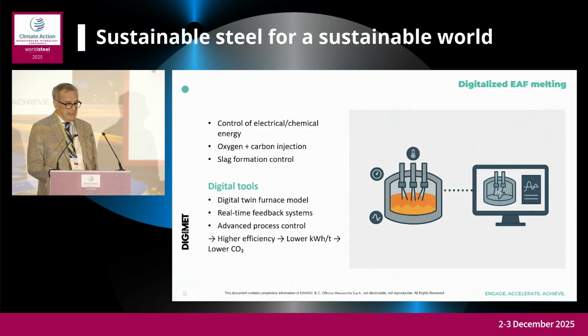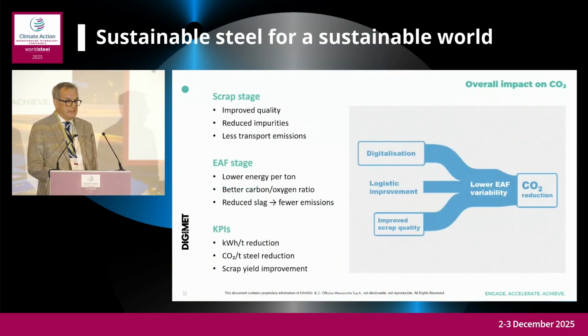Real-time data acquisition and analytics help operators anticipate critical events, stabilize the process, and reduce the tap-to-tap time. The outcome is lower energy intensity and reduced CO2 emission, always the same. At the end, if we look at the overall impact, digitalization improves scrap value, enhances batching, increasing electric arc furnace efficiency, reducing both energy and carbon consumption. And by reducing scrap impurities, the process becomes more stable, energy drops, and consequently CO2.